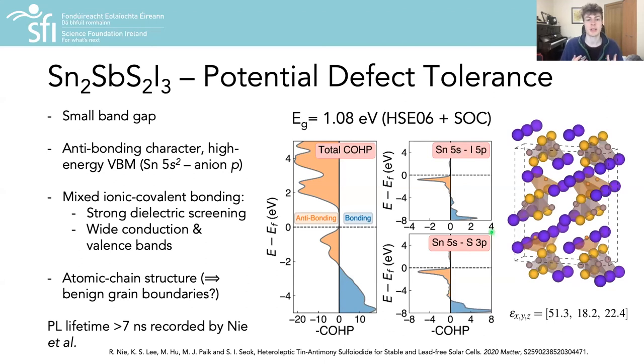Additionally, the atomic chain structure of this material along these stoichiometric chains along the A direction could result in benign grain boundaries with no broken bonds and thus minimal recombination activity, as has been noted in antimony selenide, for example.